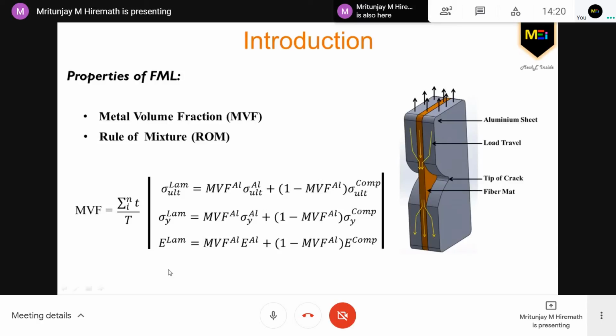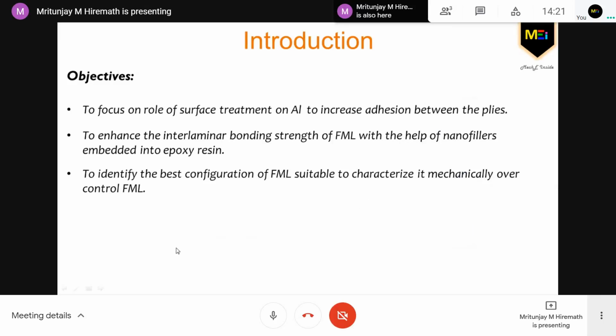If we look at the calculation of the properties, it is the same as the formula used for conventional composites. For instance, if I want to calculate the ultimate tensile strength of the whole laminate, it depends on the metal volume fraction and the constituents' ultimate tensile strength. So here it will be the aluminum ultimate tensile strength and the composite ultimate tensile strength. Similarly, the strength of the laminate and the modulus of the laminate are calculated.